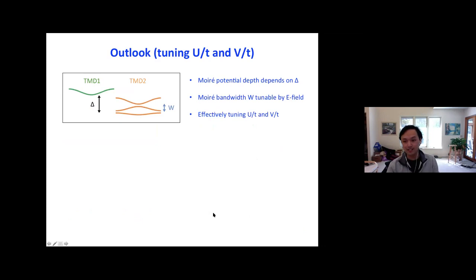And finally, I just briefly mention that not just can we tune the filling factor of this moiré system, but we can also tune the interaction strength, say, for instance, the U over T or the V over T. The idea is to tune the band separation between the moiré band in one TMD layer and the moiré band in the other TMD layer, which effectively tunes the moiré potential in the system and therefore the bandwidth of the moiré flat band. So if you tune this distance by an electric field, you can tune the bandwidth of the system. And effectively you are tuning U over T or V over T.